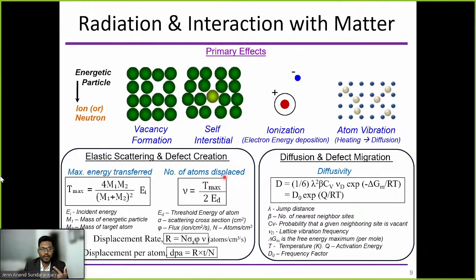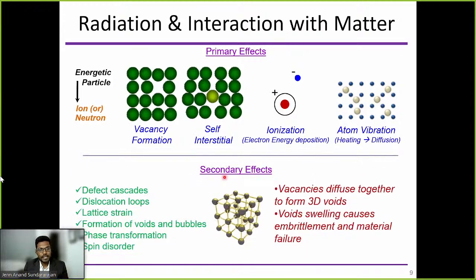So it can form different cascades, it can form voids, it can form dislocation loops. A whole plane of atoms can be dislocated. A whole plane of atoms could be missing there. And it can cause so many intrinsic property changes within the material. Okay, and it can cause vacancies and voids, which eventually lead to embrittlement and material failure. So this is the basics of radiation interaction with matter.